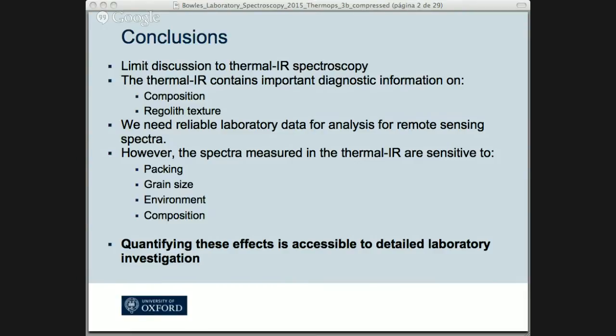So really what we're trying to say is that the thermal infrared does contain important diagnostic information on the composition, that's kind of a given, but also on the regolith texture. I'll show you some laboratory data that shows this quite nicely. We of course need reliable laboratory data for remote sensing spectra, but in the thermal infrared in particular, you're really sensitive to all these concepts such as packing, grain size, the environment you're measuring them in, and the composition as well. This is something that came out both from Josh's talk and other talks over the last few days for asteroids, and it's really important also for the moon. But we're getting pretty good at this now, and quantifying these effects is accessible to detailed laboratory investigation.